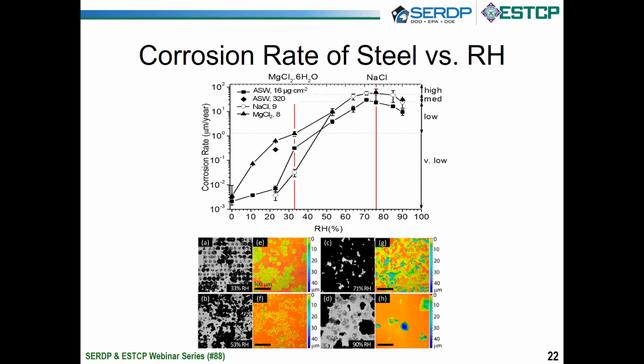Interestingly, as you jump above that deliquescence point, you can see a distinct change in the behavior of this morphology. There's much less corrosion, but the corrosion you do see turns out to be very deep. The reason is that as you go above the deliquescence point, you get fully deliquesced salt, the droplets coalesce into a thin film, and so you have a large cathode. Instead of corrosion being driven by just what's going on around the edge of a droplet, the cathodic reactions occur at distances. So you get single or small anodes that become very deep.